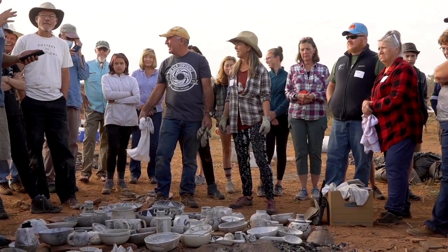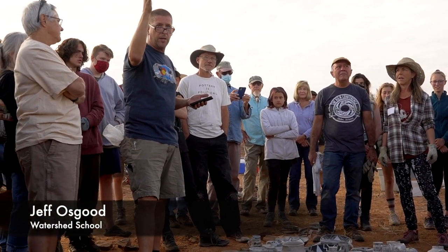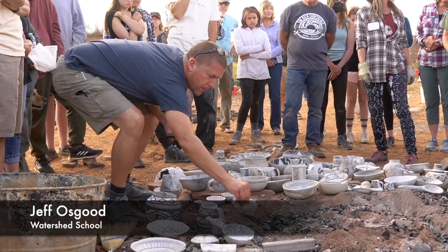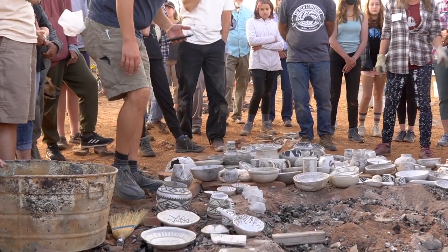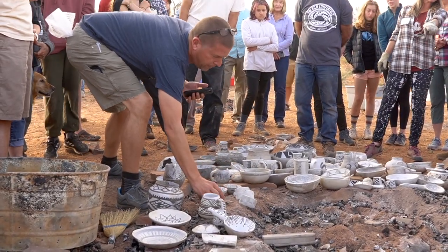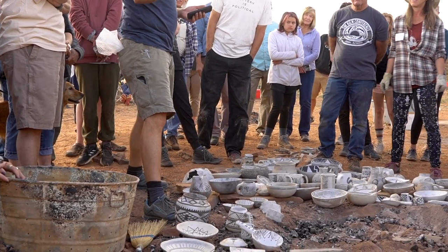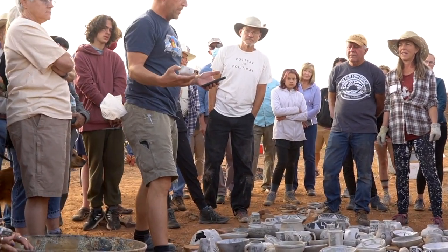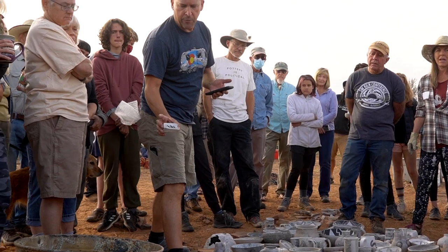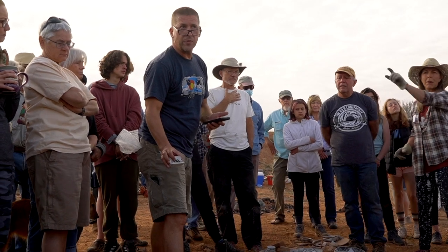So we did a range from roughly 875 Celsius to 1060 on the high end. Okay. Wow. So that's an 012 to 04. So they were like this. I'm going to have to keep you guys around. If you look at these cones, they're all just standing straight up. So that top part, even where that bowl blew out, was not hitting 875. Down a quarter of the way, you've got your 875 down, and then this second one here. The second cone starts to go at 895 Celsius, and it's starting to go.